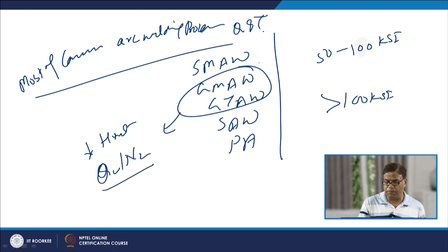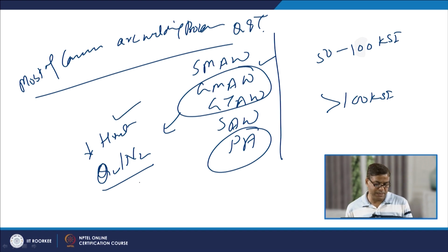Proper protection by the shielding gases in the case of GMAW, GTAW and plasma arc welding helps us develop good quality weld joints with less heat input, and the gases present in the form of oxygen and nitrogen in the weld metal are also reduced. So, Q&T steels of high yield strength, greater than 100 KSI, are mostly preferred to be welded by GMAW, GTAW and PAW processes.